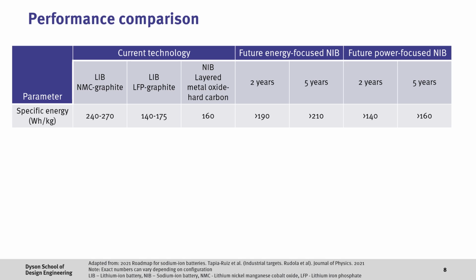Now, it's important to remember that there are a number of different lithium-ion and sodium-ion battery configurations. However, if we caveat this, it's useful to put some numbers to each technology to allow us to compare them. For specific energy, high nickel lithium-ion batteries are generally at around 270 watt-hours per kilogram. For high power lithium iron phosphate cells, this is more at around 170 watt-hours per kilogram. For a sodium-ion battery with a layered metal oxide cathode and hard carbon anode, there have been reports of specific energies of around 160 watt-hours per kilogram, which is very respectable.